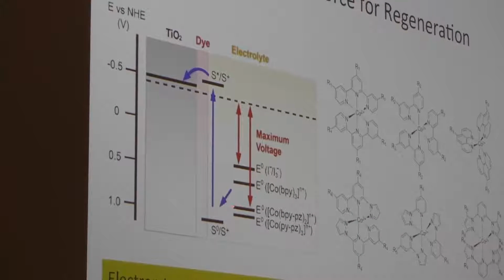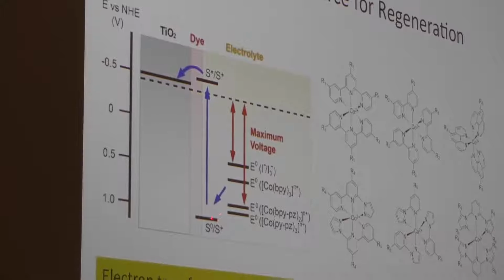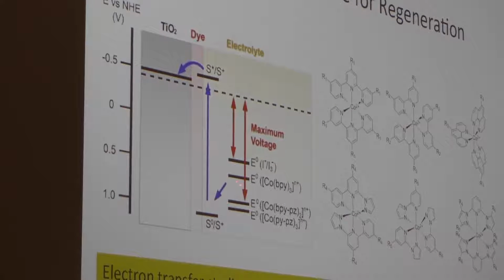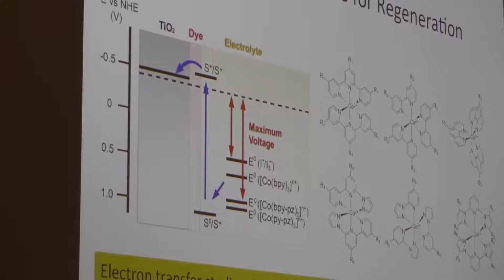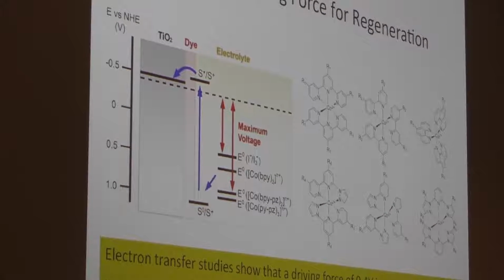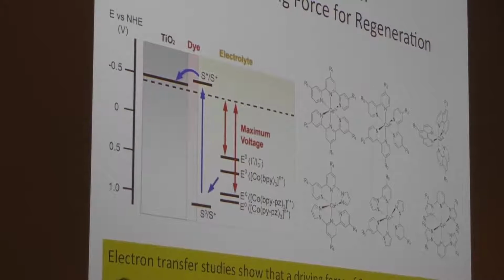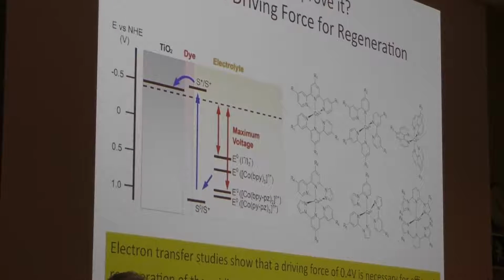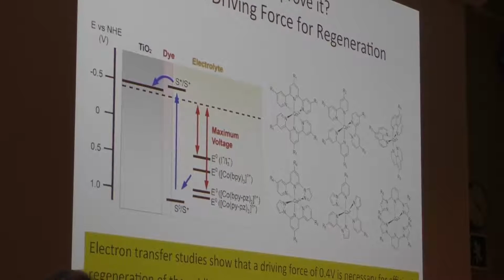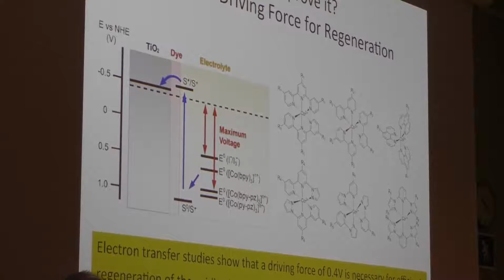When you do that, you also slow down the regeneration, so there must be some optimum. Of course, when you go more and more positive, you should also increase the voltage, but there is an optimum. And to make a long story short, we found that for cobalt we need 0.4 volt in driving force to efficiently regenerate. If we are lower than that, with higher redox potential, the regeneration becomes too slow, and we have problems with recombination because of that.